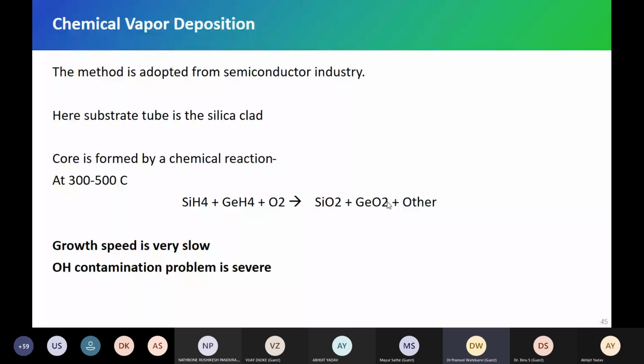Another thing is water contamination. Because we are passing different gases, and these gases are not really dry. We say gas, but it contains a lot of water vapors. If there is water vapor, it will give huge OH related loss. I will show you, I think there is a slide on that. OH is not good for optical communication because it creates a loss at 1383 nanometer. If there is huge OH content, that attenuation can go very high. So we don't want OH, and there is a huge problem of OH here in chemical vapor deposition. Otherwise it's very simple: put in SiH4, GeH4, add oxygen, set the temperature, and you get that material. To avoid these problems, I'll skip this slide.